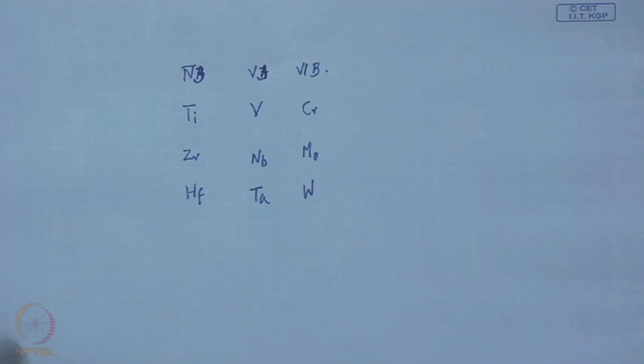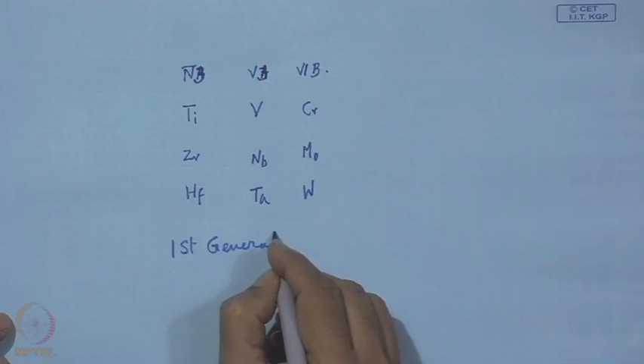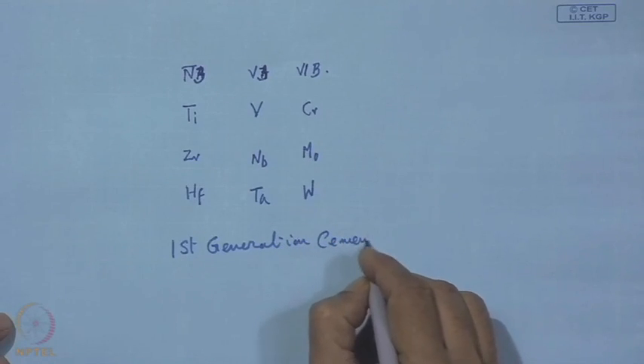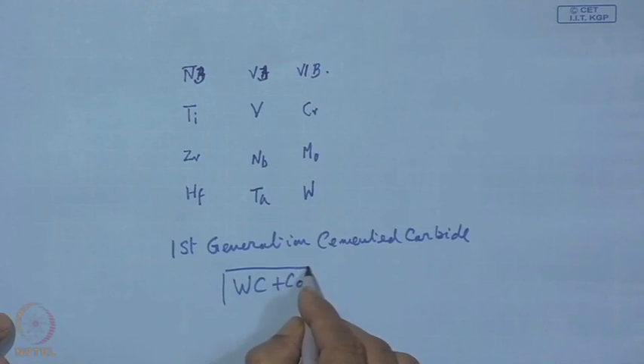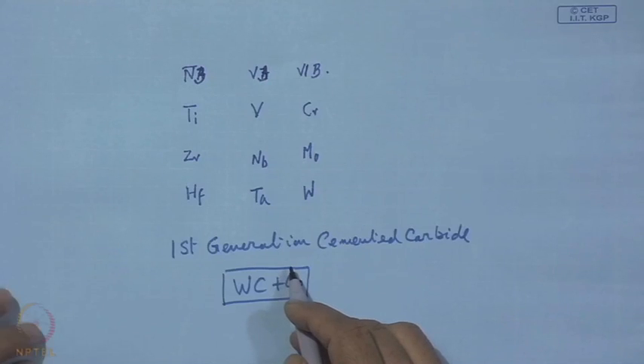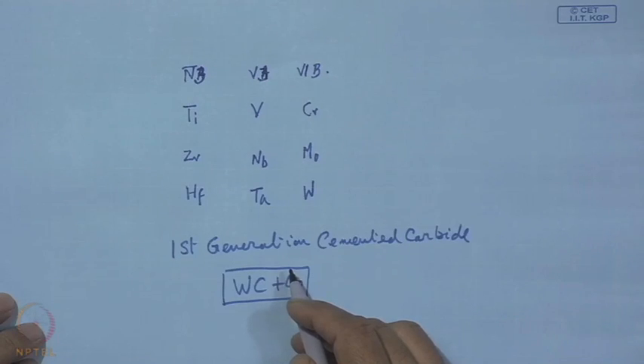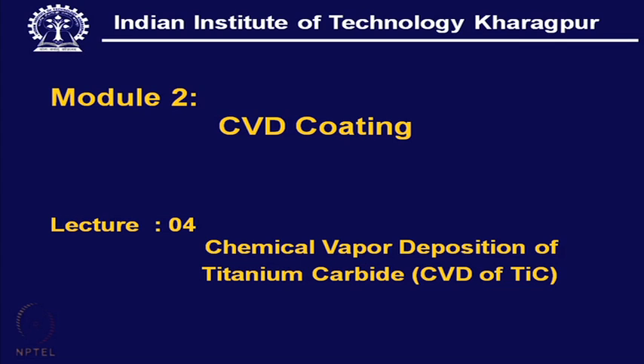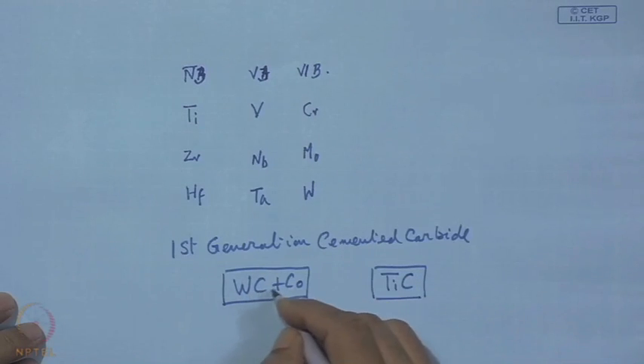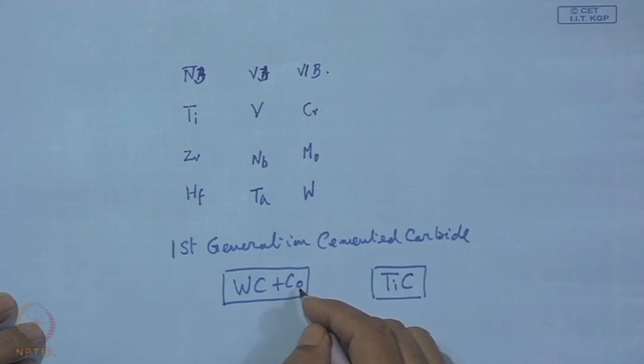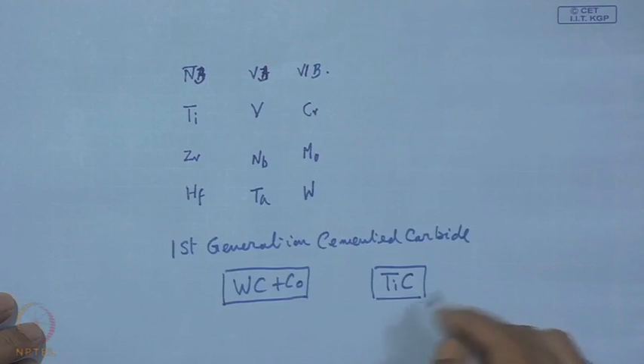The first generation cutting tool — cemented carbide — was formulated with tungsten carbide and cobalt. However, it was found that this tool, though very effective for machining of cast iron, was not that successful in the machining of steel. It was further revealed that a small percentage of titanium carbide within this tungsten carbide-cobalt matrix can improve the performance of the tool remarkably while machining steel.